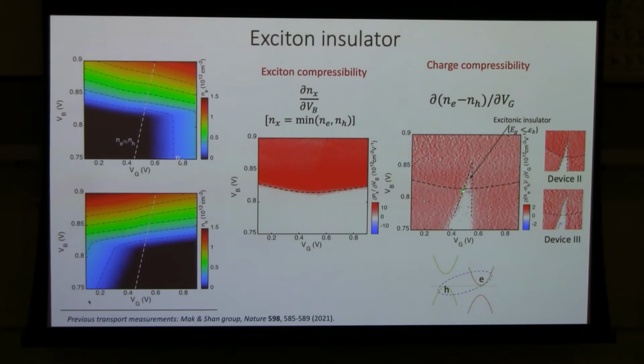But there is a very small triangle region where although we have net electron and hole density and we can inject excitons into the system, we cannot inject individual electrons or individual holes into the system. And this region is known as the exciton insulator. Basically, that means you can inject excitons, but not the individual carriers, and it can be reproduced in many different samples.